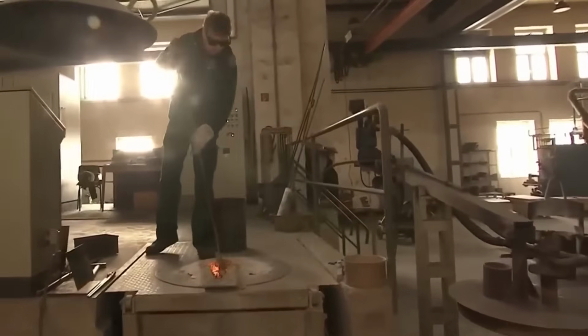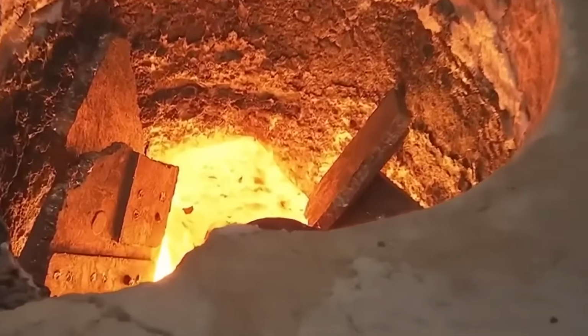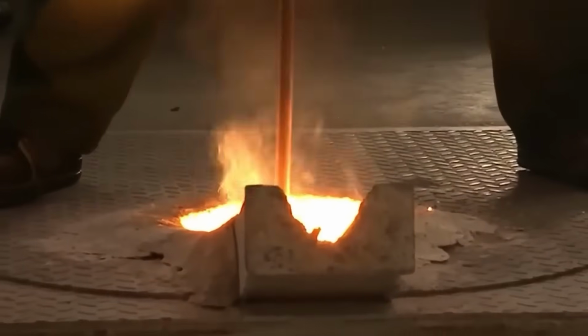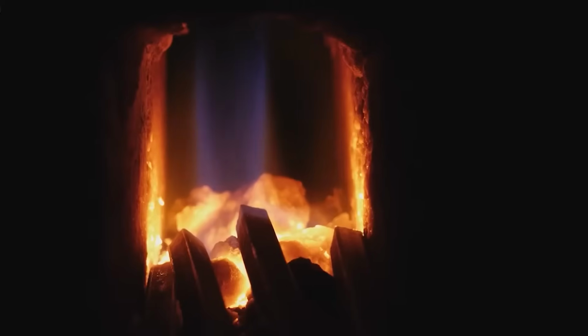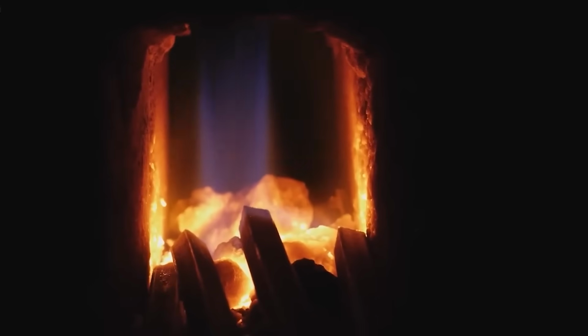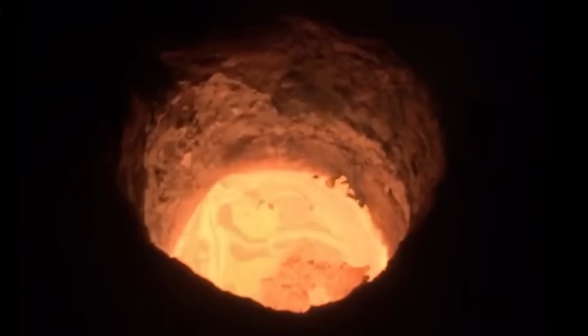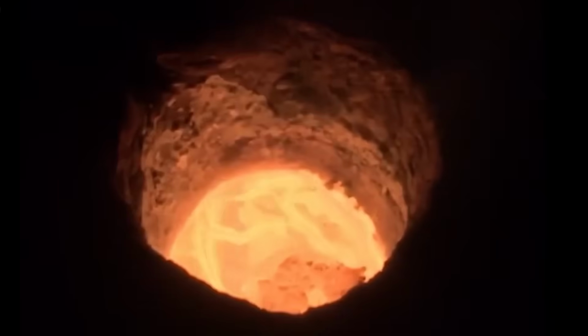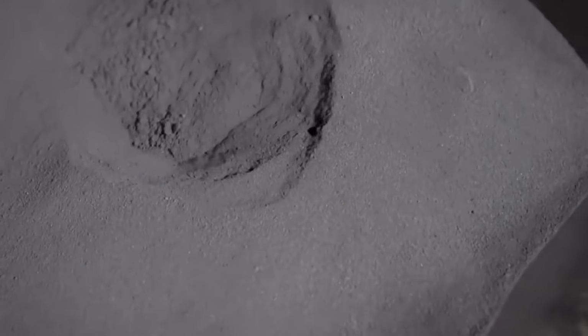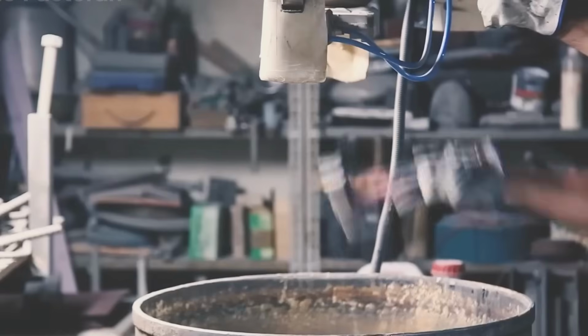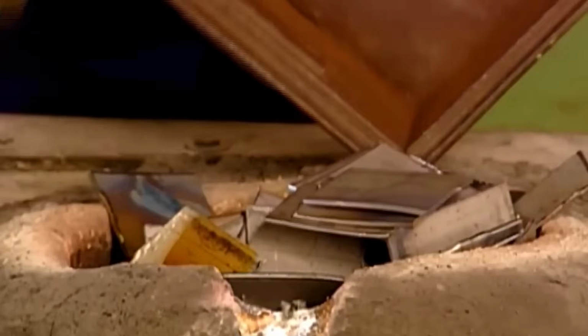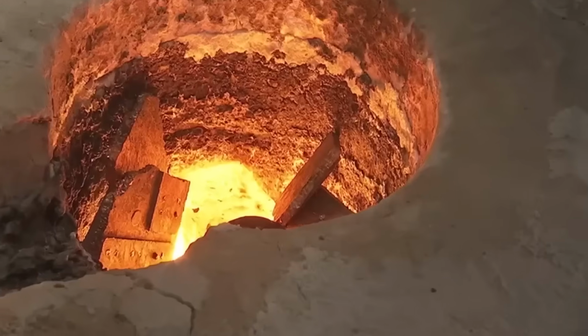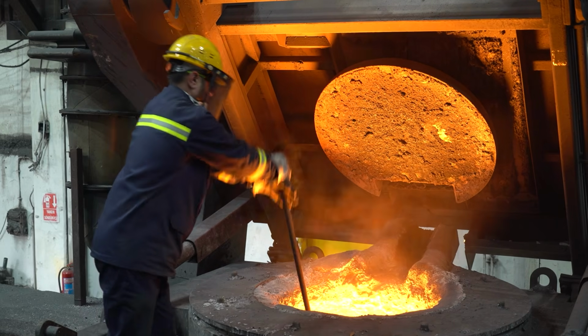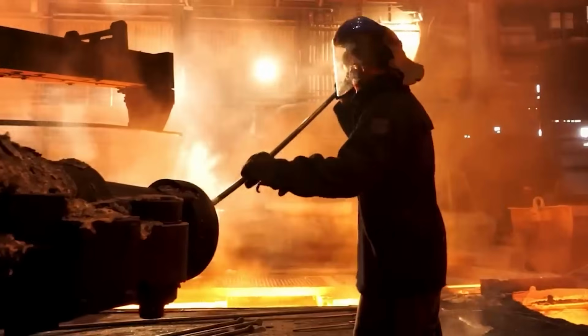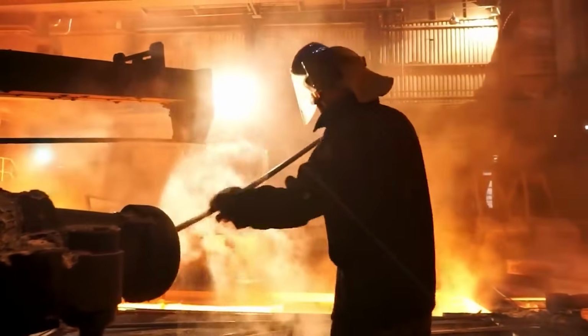The next step is preparing the neodymium-iron-boron alloy, the foundation of every neodymium magnet. The materials are melted in vacuum furnaces under a controlled atmosphere to prevent oxidation, since neodymium is highly reactive with air. The standard composition is approximately 30% neodymium, 1% boron, and the remainder iron. This alloy is heated to temperatures above 2,370 degrees Fahrenheit until all elements are completely melted and homogeneous.